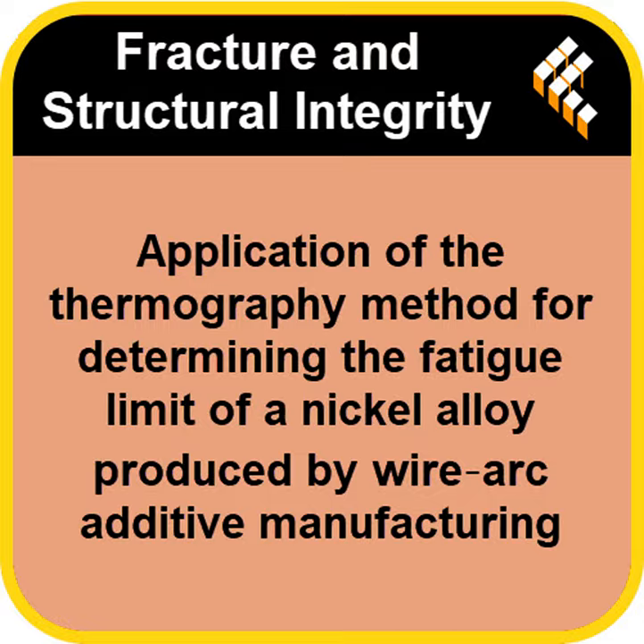Oh, absolutely not. And the researchers here did something really crucial. After printing, they put the material through a special refinement process. They physically deformed it, or forged it, with a high-frequency pneumatic hammer. So they were basically hammering the 3D printed layers. Essentially, yes, while it was still warm, around 200 to 300 degrees Celsius. This interpass forging helps crush any of those internal voids or imperfections from the printing process. It really improves the final mechanical properties. And then a final heat treatment after that, I imagine. Correct. So you end up with this really complex, highly engineered material, forged and heat-treated layer by layer.